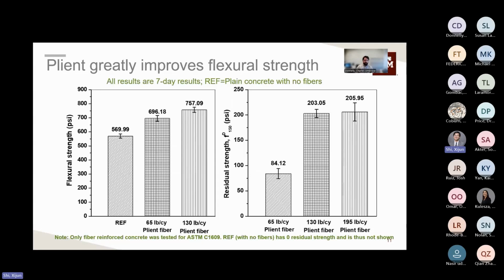On the left, you see that increasing the dosage from a reference or no Plient fibers to as high as 130 pounds per cubic yard, you see a significant improvement in the overall flexural strength. But then critically, when you compare different dosages of Plient fiber, you get significant residual strength achieved through using Plient fiber. An unreinforced or zero dosage of Plient fiber, which isn't shown in the plot here, would have no residual strength. So once the crack forms, the beam breaks. When you look at starting to dose with Plient fibers, increasing the dosage to a certain point significantly improves the overall flexural strength or residual strength of the concrete.